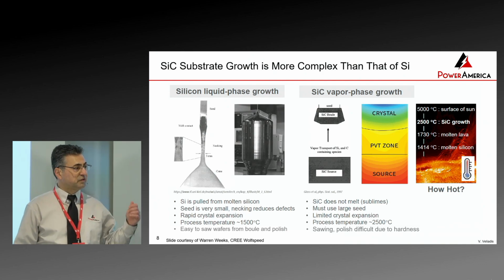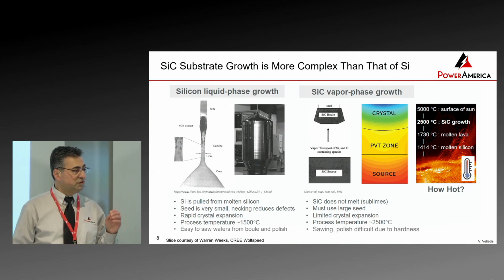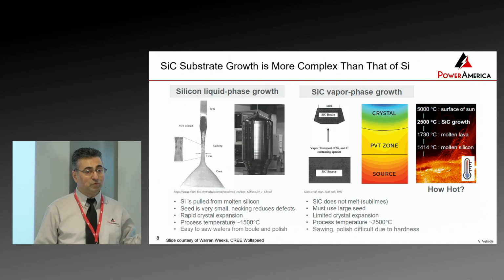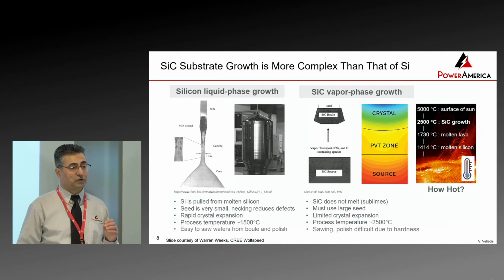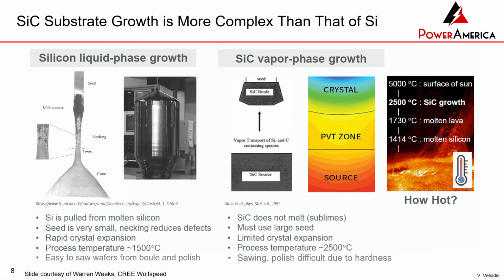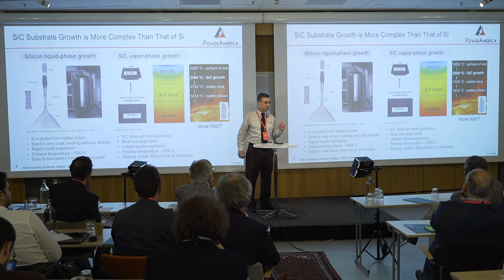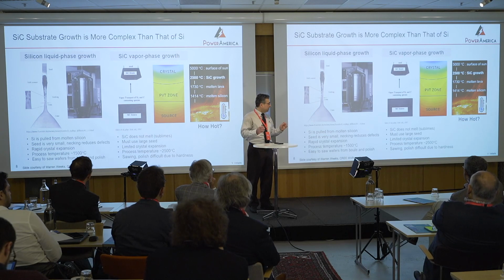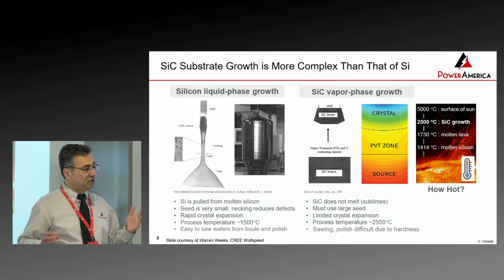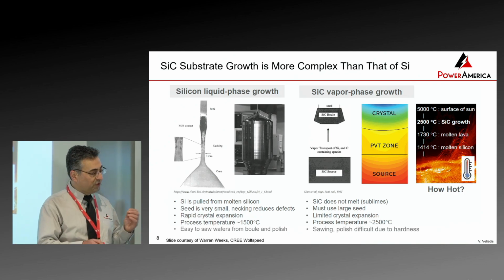First of all is the substrate. Any new material, gallium oxide, diamond, aluminum nitride, gallium nitride, you need to have substrates that are cheap and can compete with those of silicon. So cheap and low defects, planar, and so on and so forth. Well, with silicon carbide, there is a problem, right? You need to go at very high temperatures, 2,300 to 2,500, versus 1,500 degrees for silicon. And in silicon, you basically have a melt, and you're pulling the material, and this necking process helps you reduce the number of defects. And that's not the case in silicon carbide, where you need a very good seed layer. So with silicon carbide, the process of making the substrate is more labor intensive. The boule is a lot slower to make. It's a lot smaller in length. Diameter is a problem. You have limited crystal expansion, and because it's a very, very hard material, polishing is a problem.